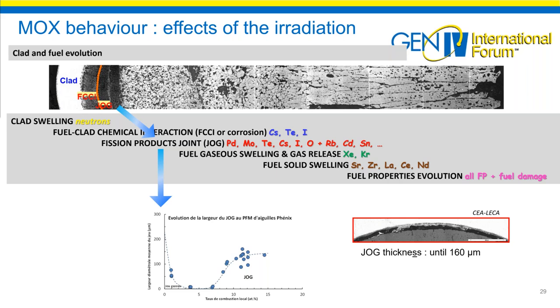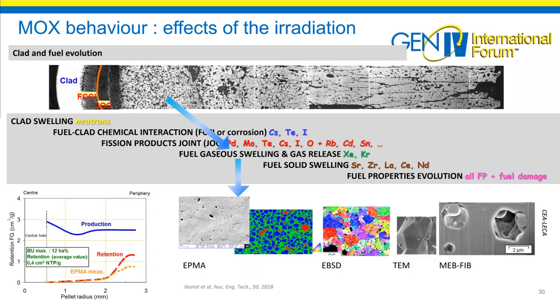A reduction of several hundred kelvins is expected in the fuel thanks to the good conductance of the jog in the gap. So we have observed that jog formation starts around 7 atom percent, and we assume that there is no mechanical effect because it's a plastic material with an actual extrusion in the gap. So next slide, please.